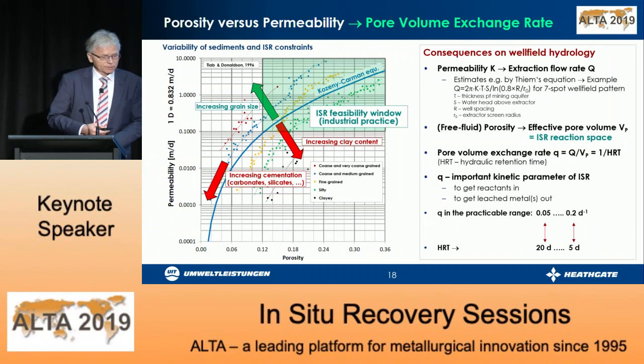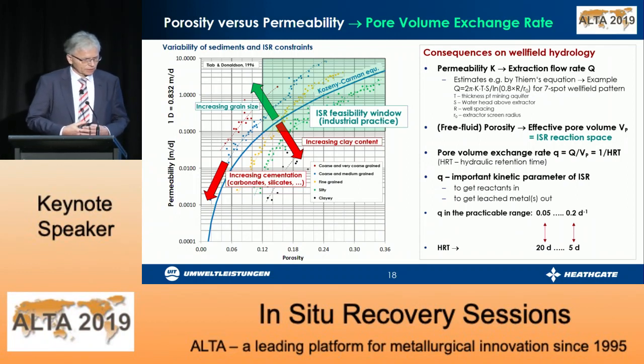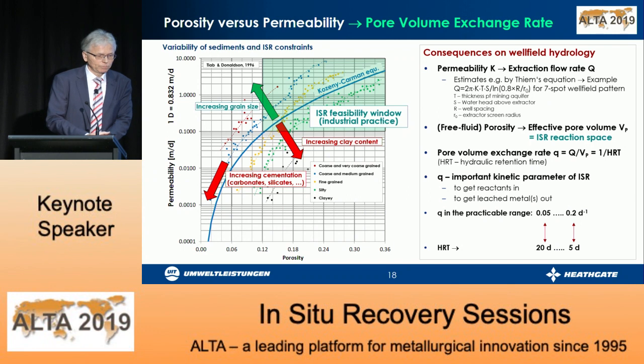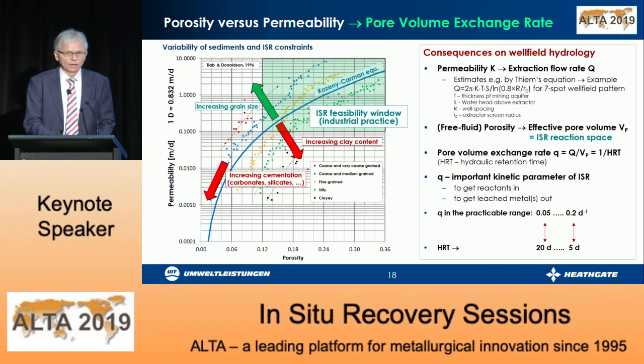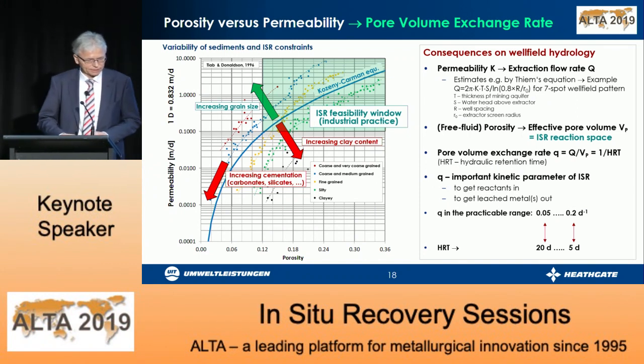The consequences with regard to wellfield hydrology are summarized here. The permeability results in an extraction flow rate that can be simply estimated. Again, the free fluid porosity defines the effective pore volume. This is the reaction space we have to rely on in the underground. The pore volume exchange rate Q is defined by this ratio, volumetric flow over the pore volume. This is the inverse of the hydraulic retention time.